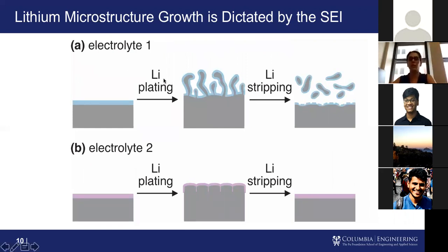The main hypothesis behind all of this work is that you have some electrolyte, and as soon as you dip your lithium metal into the electrolyte, you form some type of solid electrolyte interphase layer, this SEI. This can be a good SEI or this can be a bad SEI. If this is a bad SEI, whenever you start plating lithium on the surface, you get this dendritic-like growth that could pierce the separator and cause your cell to short circuit and light on fire.